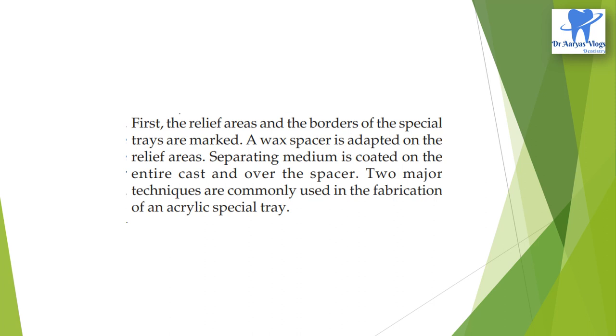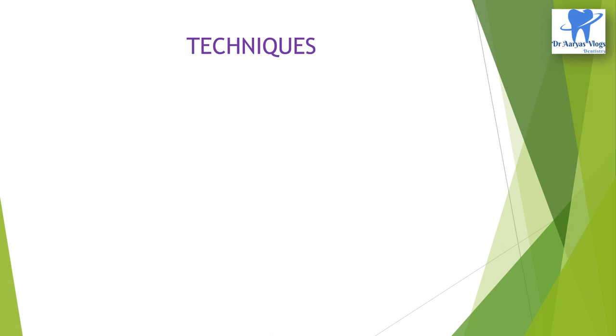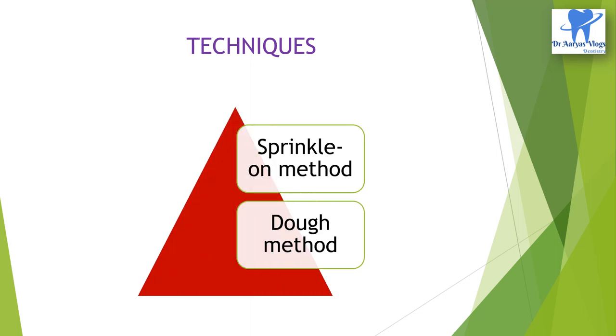So coming to the fabrication, first the relief areas and borders of the special trays are marked, and the wax spacer is adapted on the relief areas. Then separating medium is coated on the entire cast and over the spacer. Two major techniques are used for custom tray fabrication: sprinkle-on method and dough method. These should be fabricated 24 hours before the impression procedure to ensure adequate degree of polymerization. What about the shellac trays? 6 hours prior to the impression procedure. So self-cure resin trays should be fabricated 24 hours, that is, 1 day before the impression procedure. We'll discuss the two techniques in detail.